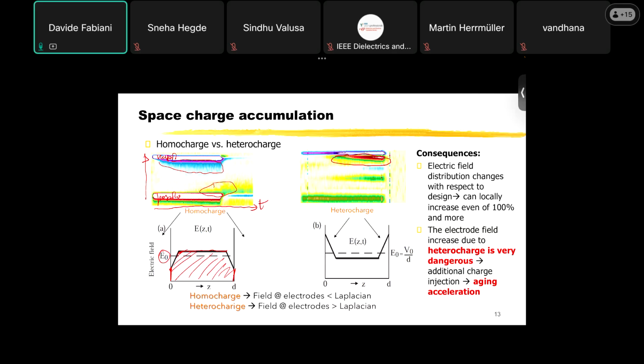But the problem is that this increase at the interface between electrode and the insulating material is very dangerous because, increasing the field, it can provide more injection of charge inside the material, because the injection of charge is field dependent. So if you increase the field due to heterocharge, then you can inject more charge in the material. And this can create a further distortion of the electric field. So it could be a process that can provide very quickly cable insulation failure. Okay, so heterocharge is very, very dangerous. While homocharge is not so dangerous. We will see a case where also homocharge can be a little bit dangerous.